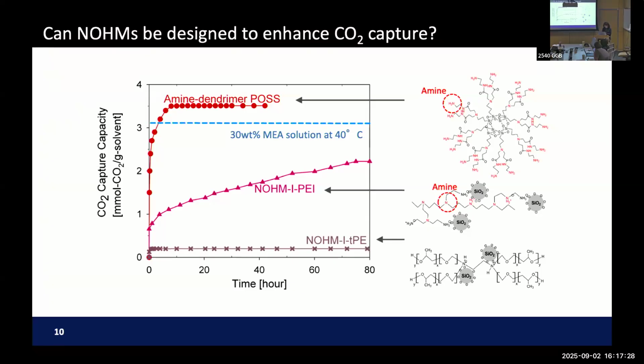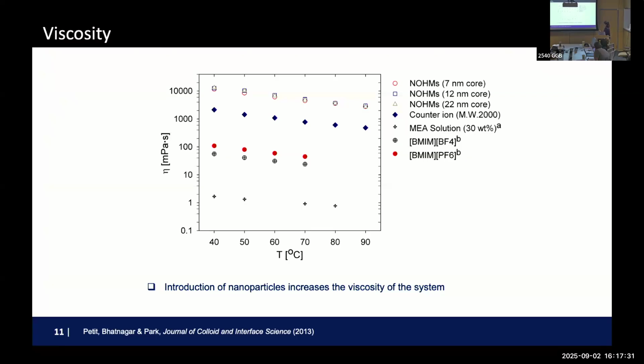So a lot of my friends, like here, this is the data showing the viscosity versus temperature. These are the amine-based liquid solvents. It looks like water. Very easy to design a reactor. You can do spray tower, trickle bed, many different designs. Mass and heat transfer, very easy. There are some examples of ionic liquid. These are our NOHMs material. Our friends, including John Brennecke at UT Austin now, said we can reduce the viscosity to maybe 20 or 40 centipoise. And they've done it by changing the hydrogen bonding network. In fact, we can do something similar with NOHMs and bring down viscosity.